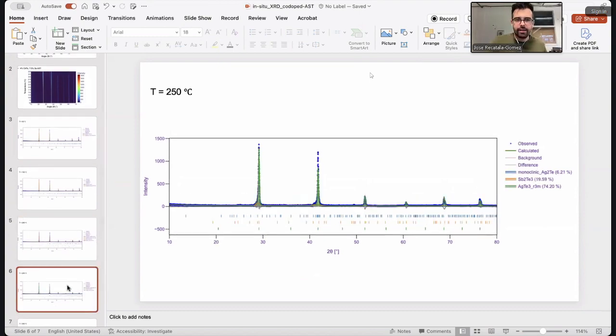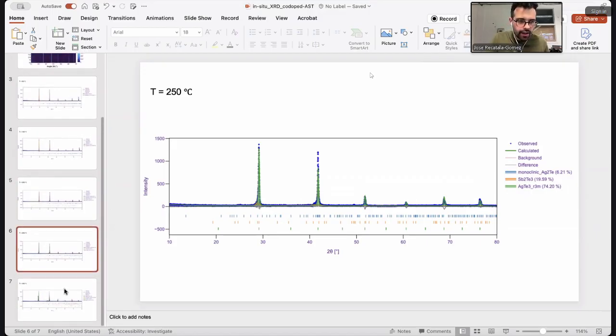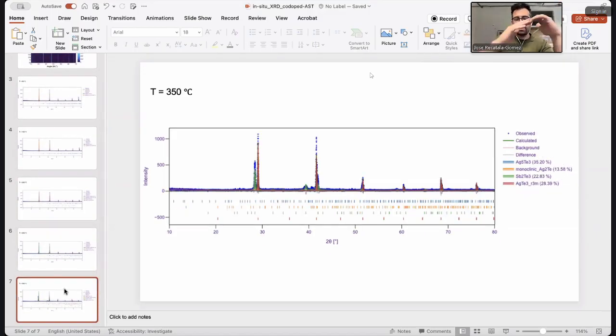So here's the pattern at 250. There is much more antimony telluride. And when you get to the maximum temperature of the scan, which I set to 350 because that's what we have in the paper, essentially, it's completely decomposed into antimony telluride, and we have this silver telluride appear as well.